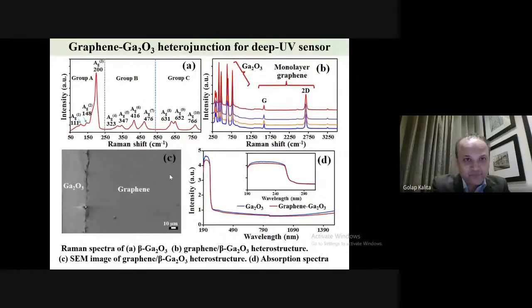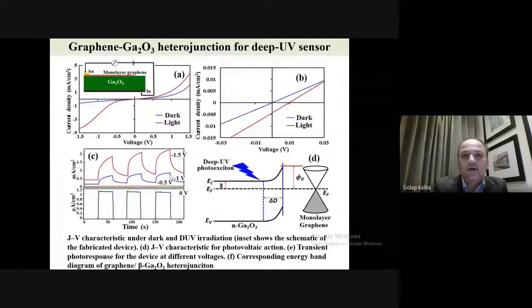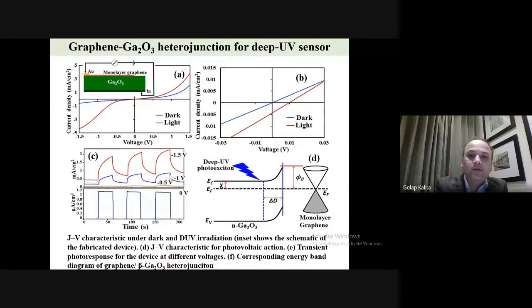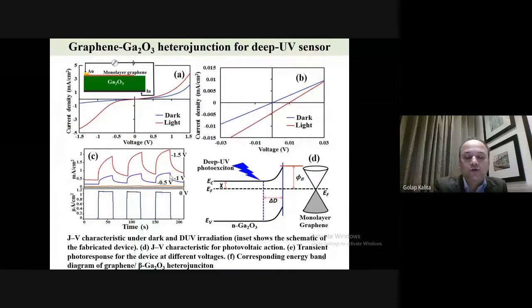Then this is the graphene gallium oxide heterojunction. We can make a graphene and gallium oxide heterojunction similar to graphene gallium nitride. In this case also, we look at the photoresponse properties. Because it has a band gap of 4.8 electron volt, we illuminate it with around 254 nanometer UV light. It comes in deep UV, beyond the solar spectrum, so it becomes solar blind.